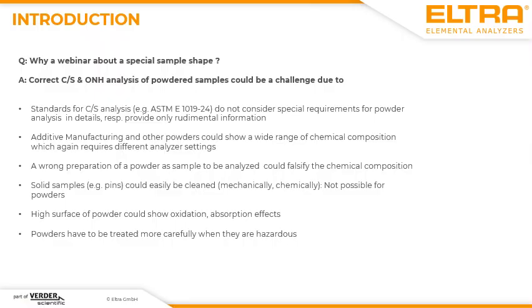And this is also the other thing which is important to know when you are dealing with the analysis of powders. The high surface of this powder could cause, I would say, irritating results due to oxidation processes or maybe other absorption processes. And one thing which is listed last is more or less one of the most important things. When you have powdered samples, you have to take much more care about safety, because hazardous ingredients could cause much more trouble when they are present in a finely divided powder.